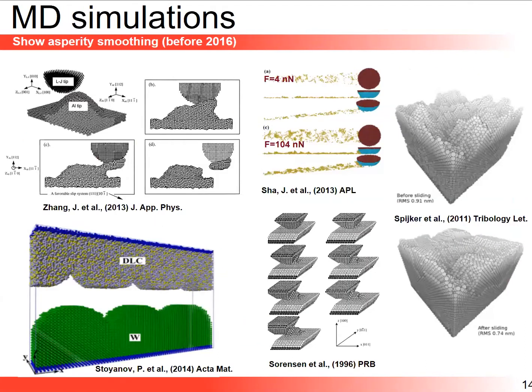Also, for the inside story, this finding did not come directly to us. It was a struggle over many, many years. And not only for us, I would say for all the molecular dynamics community looking at wear mechanisms. I can say that up to 2016, all the reported data, to the best of my knowledge, showed the ductile mode of deformation and not the brittle mode. So here, to illustrate my point, I take the data of Peter Spijker, who was a postdoc in my team 10 years ago. And we did simulations of two rough blocks sliding on top of each other.